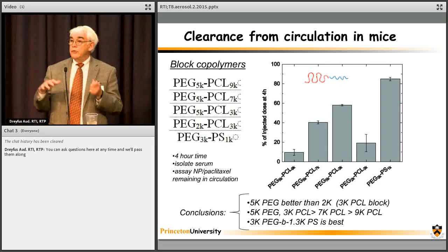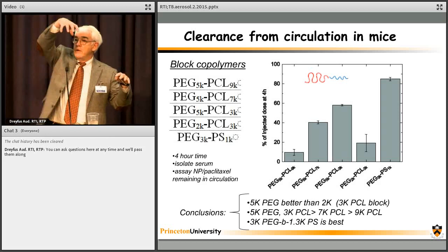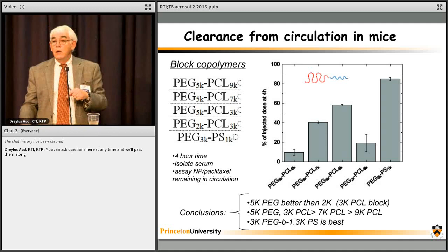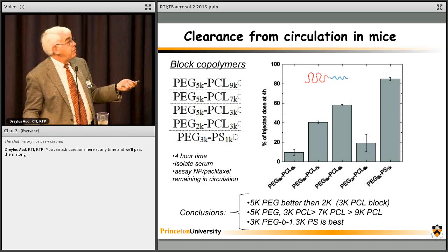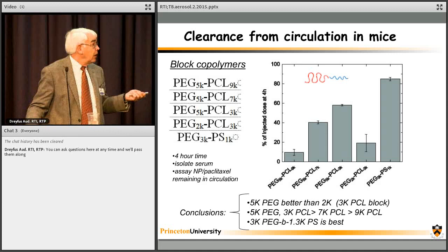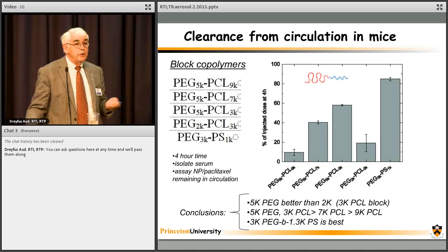What's happening is that the bigger hydrophobe is occupying more area at the nanoparticle surface relative to that PEG chain. And if I occupy too much area at the surface, then proteins can adsorb at that less well PEG-protected surface. The winner here is actually a polystyrene. A 2.7K PEG, 1.6K polystyrene. And that gives, after 24 hours, 80% of the material still circulating in the animal.